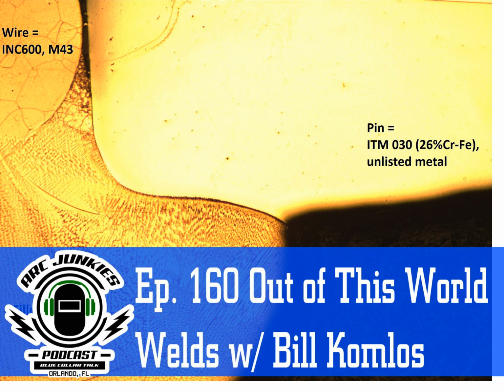So you're just spraying liquid nitrogen on the backside while he's running it in there? Now you build a tub. We actually, I had a dewar of liquid nitrogen given to me, and it would take me 6 hours to weld one of these joints, because we pump in about 18 pounds of weld metal into just the flange.